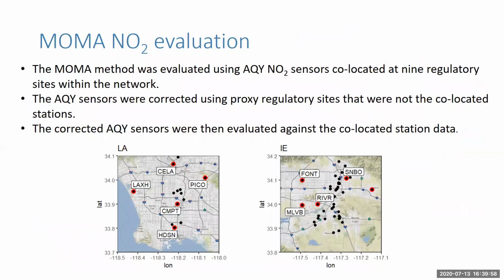The MOMA method was developed and evaluated using AQY NO2 sensors co-located at 9 regulatory sites within the network, shown here in the graphs. The AQY sensors were corrected using proxy regulatory sites that were not the co-located stations. And the corrected AQY sensors were then evaluated against the co-located station data to give us an indication of how good the correction was.